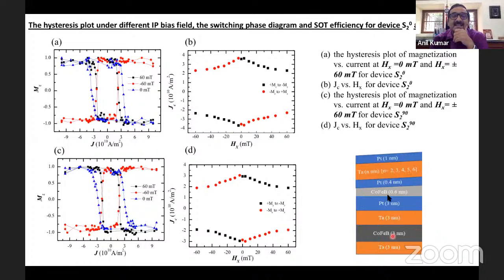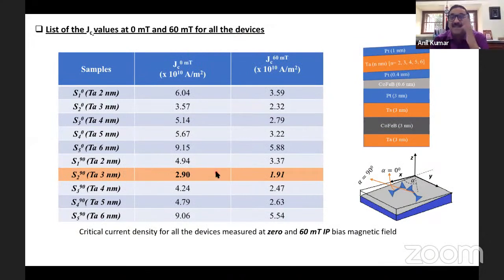Now you can see that in this kind of a structure, even at zero magnetic field, you are able to switch. Now the critical current that is needed to switch has gone down further. And there is no gray region. That means without applying an in-plane magnetic field, you are able to switch the magnetization. So the state of the art right now, what we have achieved, is less than 2 into 10 power 10 ampere per meter square. So our search is going on to expand the complexity of this and exploit different kinds of physics and use it here to reduce this current further so that the future spintronic devices will be consuming less electrical power.